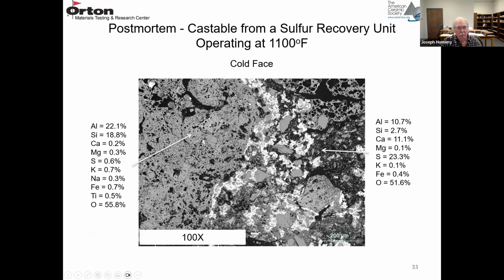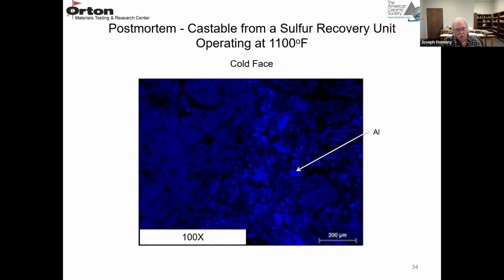This is the coarse aggregate. It's alumina, silica, and oxygen. And then this is the matrix, alumina, silica, and lime, plus oxygen. So this darker gray region is where the cement phase is. The bright region is the sulfur that has deposited in the material. So the blue is aluminum. So you can see the blue in the coarse aggregate. The finer pieces of alumina in the matrix are a little bit higher alumina content, so they're a little bit brighter. So you can see the fines in the matrix.